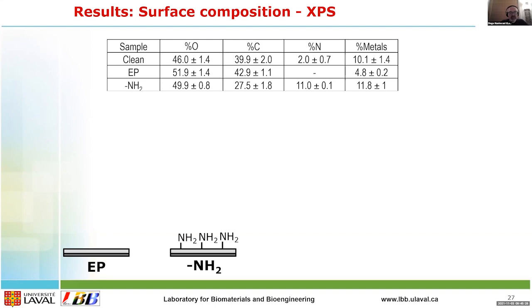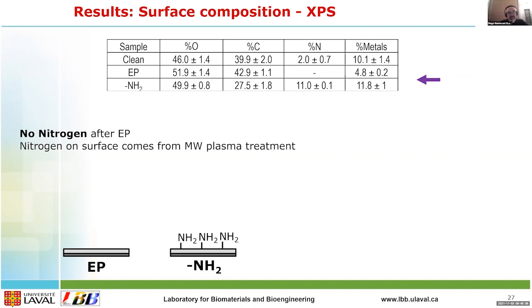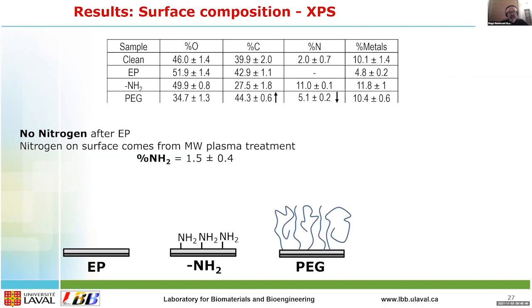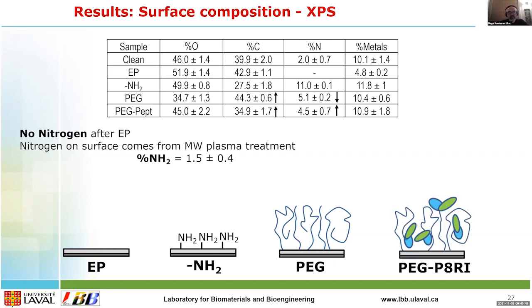Basically, you start from the electropolished condition, and then you add amine groups. There is no nitrogen after electropolishing. Nitrogen on the surface comes mainly from the microwave plasma treatment. The percentage of amine groups is around 1.5, and finally you attach the PEG, and the PEG basically increases the percentage of carbon and decreases the percentage of nitrogen. This confirms that the PEG is attached. If you then attach the peptide, you can see here just from the atomic concentration that, yes, it's feasible. You can have some peptide.